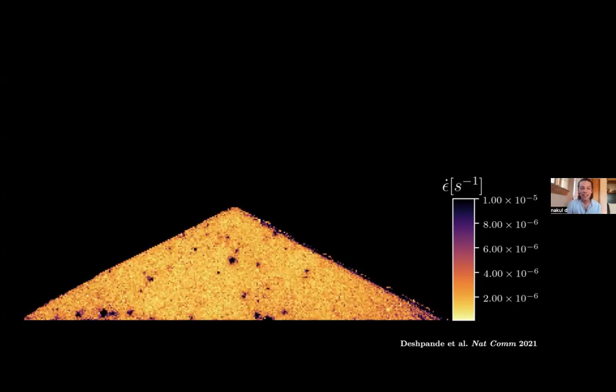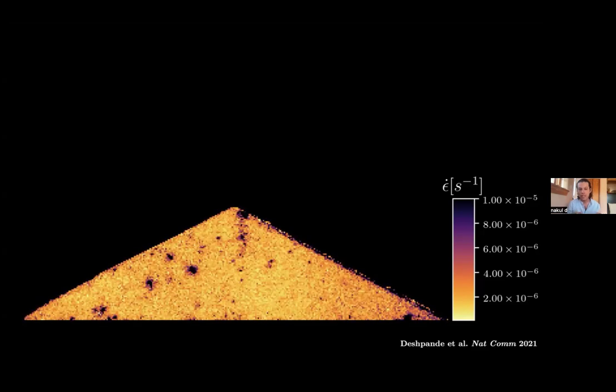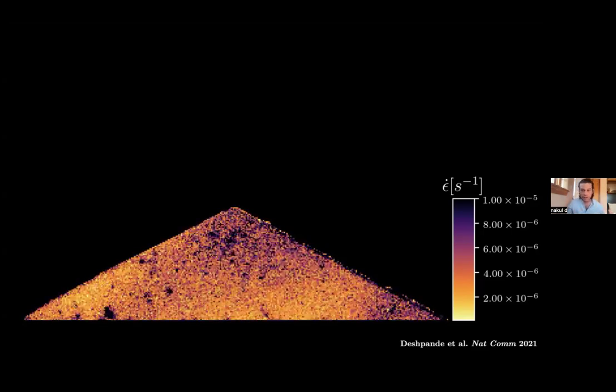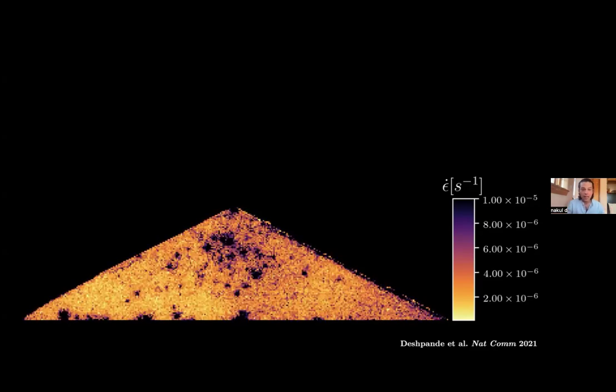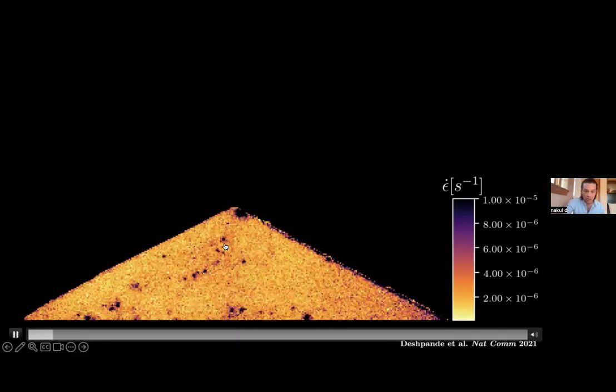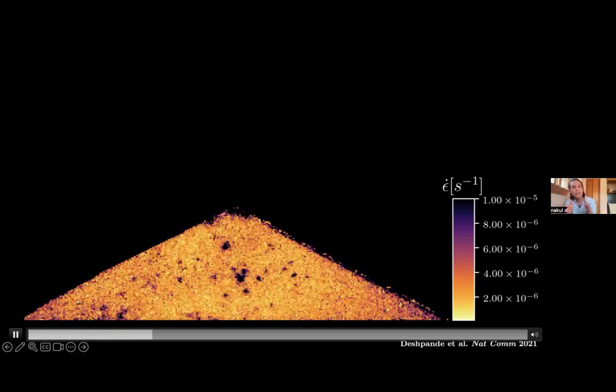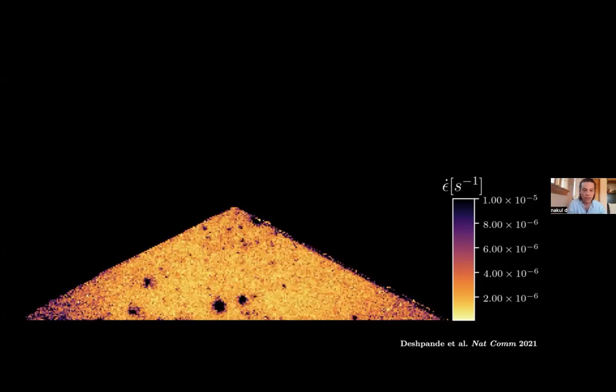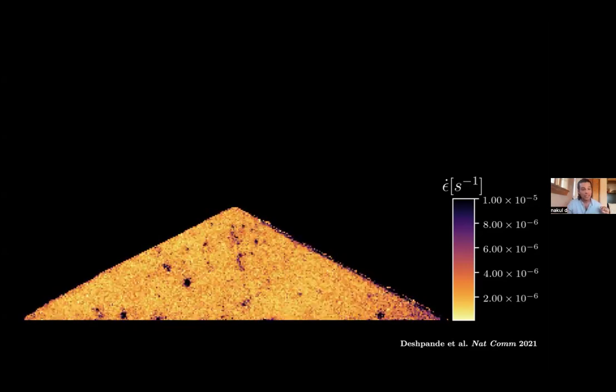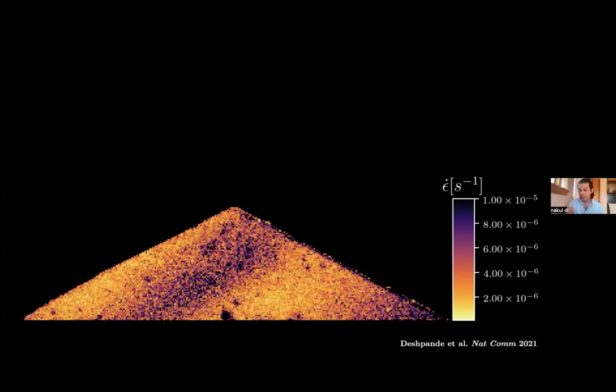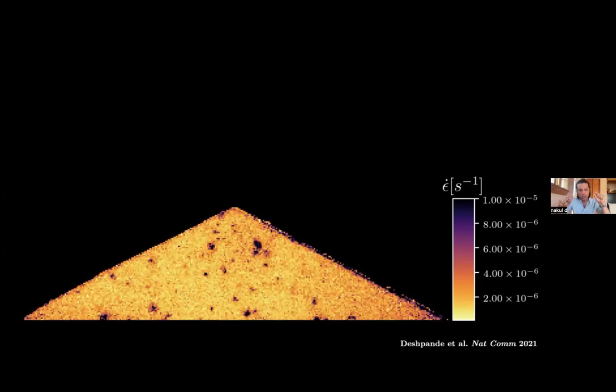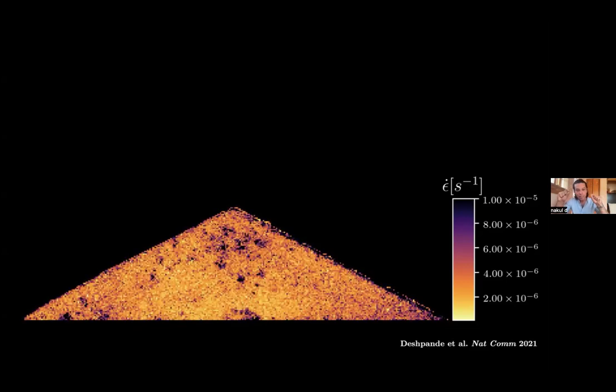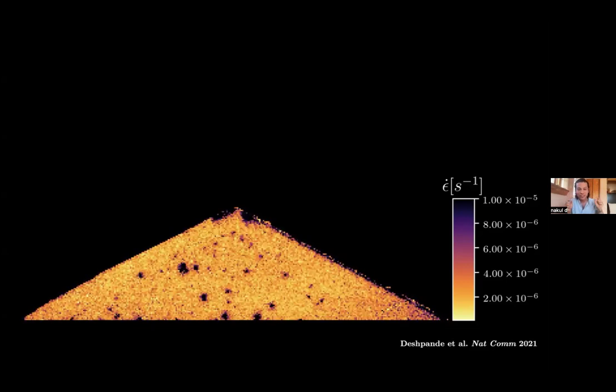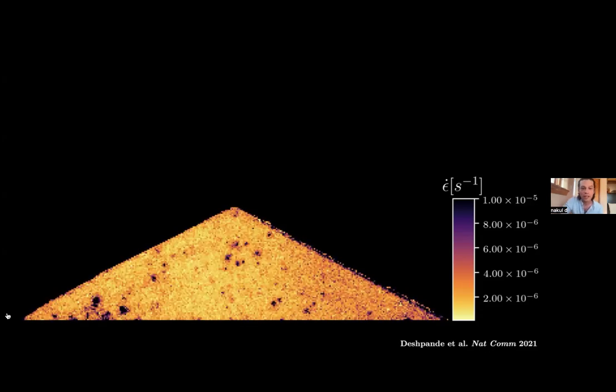So what you're looking at here is an animation for a few tens of seconds after this pile has been poured. There are no grains being added to the system. The colors indicate the magnitude of the strain that's happening within each one of these little pixels, which is a volume that encapsulates about 3 grain diameters, okay? The darker colors indicate more intense magnitudes of strain, and the lighter colors are less intense. And what you can see is that there are little popcorns, little discrete zones of deformation that pop in and out of existence for the duration of this observational window, okay?